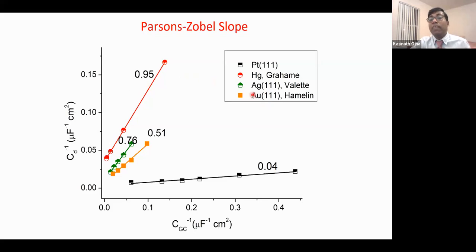But if you look at silver and gold, they deviate from 1 a bit significantly. Also, people didn't realize that this is a deviation, or that the theory is not perfect, until we found our platinum capacitance and plotted that. And from 1 it's like a huge deviation. That is because more and more ions are coming close to the electrode, close to platinum, and that leads to very high capacitance. Now this slope is much smaller because my experimental capacitance is much higher than the calculated capacitance. If experimental capacitance is higher, it is because more and more ions are coming close to the surface.